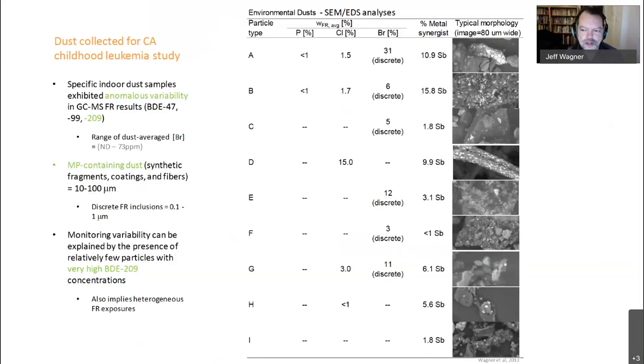But what we were able to determine with our partners was that the most variable samples were the ones that had very high concentration individual flame retardant particles, not very many of them. So for say a whole dust average sample on the order of 10 parts per million flame retardants, you would actually have just a few particles with orders of magnitude higher concentrations in the individual particles, up to 30% bromine in some cases. And that we felt could explain the variability that they were seeing. It also implies that occupants of these houses would also expect to see heterogeneous exposures depending on whether they encountered some of these high concentration particles. So that type of spatial information was really useful.